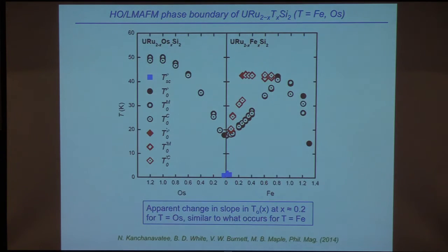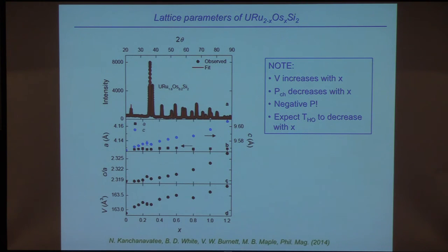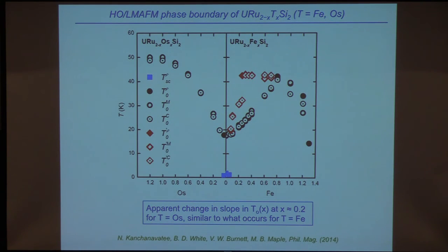And let me just make one last point. So we worked on this iron substituted system, and it turns out when you substitute iron, it decreases the unit cell volume. So we knew that osmium increases the unit cell volume, so we would have expected that things would go the other way and you would decrease the hidden order. And so what we found was shown here.